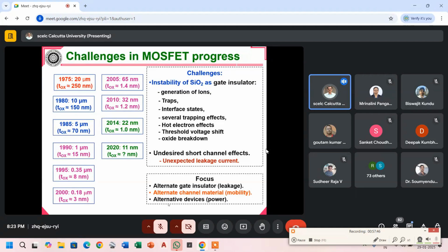And what is the fate of the oxide? In 1975, a MOSFET was using 250 nanometer thick oxide, and 20 micron was the gate length of the MOSFET. In 1980, it turned down to 10 micrometer gate length and 150 nanometer oxide thickness. In 1985, the gate length turned to 5 micrometer and TOX came to 70 nanometer. In 1990, gate length was 1 micrometer, TOX was 15 nanometer.